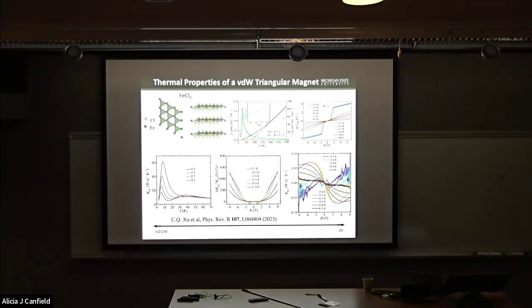We also did the thermal Hall transport studies, and again we see a very nice thermal Hall signal. Below the transition temperature, we can even see a sign change of the thermal Hall signal, which corresponds to the metamagnetic phase transition induced by the magnetic field. Again, such a thermal Hall signal could be associated with the magnon-phonon hybridization. The magnon-phonon hybridization was studied about 40 years ago through inelastic neutron scattering measurements. And here's the neutron scattering data.